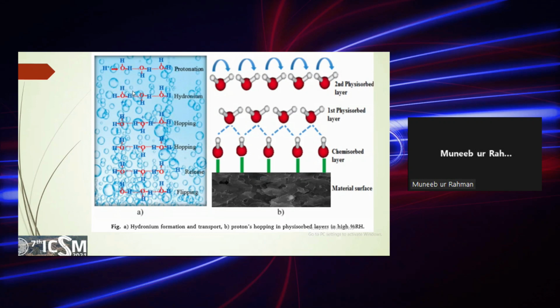this hydronium ion is formed due to the addition of this H+ ion. In the next step, this hopping mechanism starts, and this hydrogen is now bonded to the second hydrogen atom, and a hydronium ion is formed at this position. The hopping mechanism is going on toward the right, and here an H+ ion is released. So this is basically the conduction mechanism, which we call Grotthuss's mechanism.